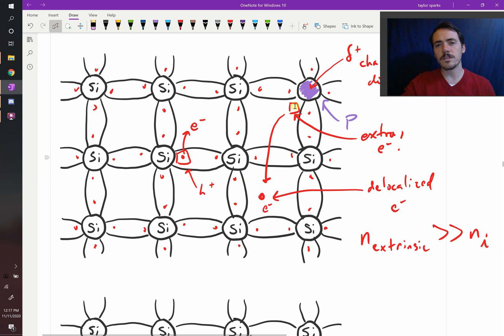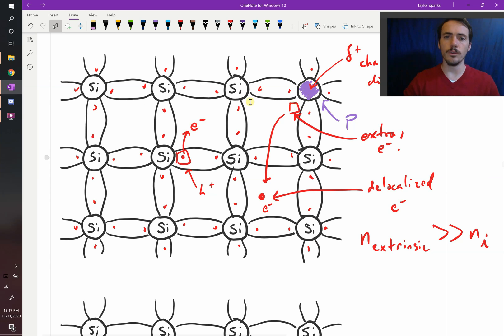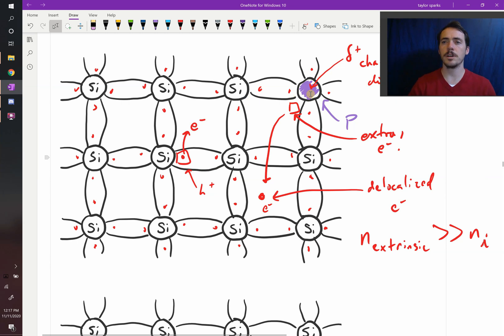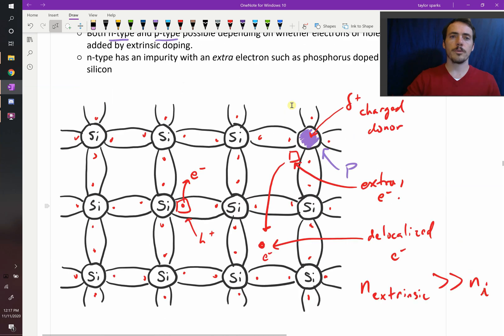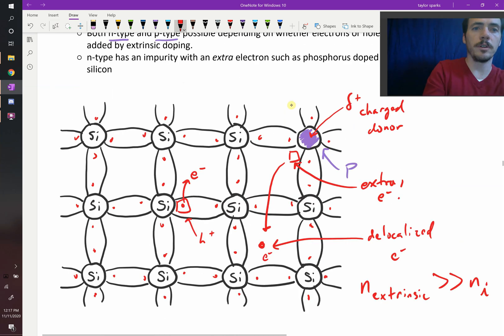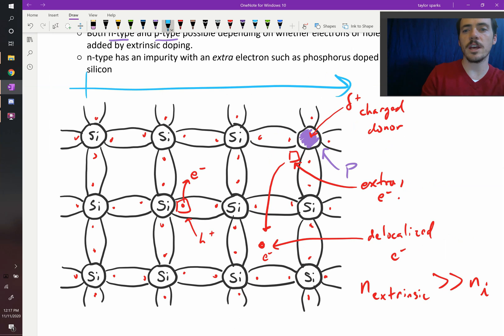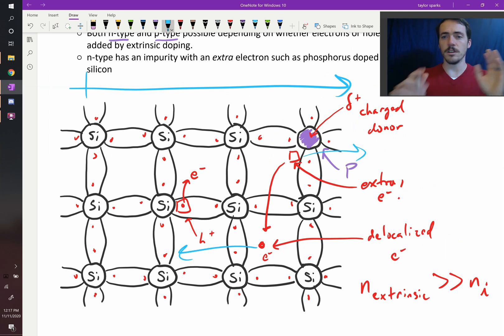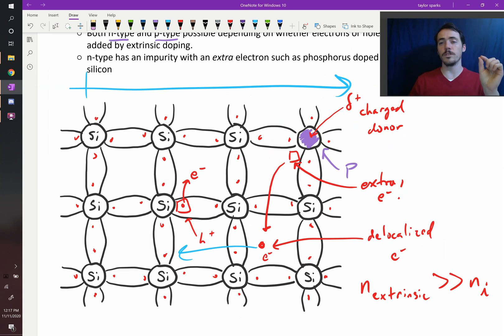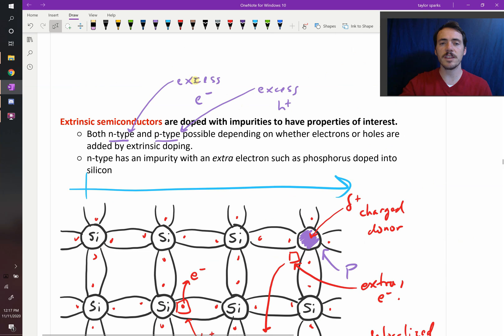Why doesn't the hole move here? Well, this hole is a site tied to the phosphorus atom — it can't move to a silicon because silicon doesn't have that spot. That's tied to this phosphorus atom because it is a group 5 instead of a group 4 atom. Previously, when we had a big electric field applied, the hole would go one way and the electron the other. That is not the case here — only the electron moves. You don't get the hole contribution. Therefore, you've made it excess electrons instead of an equal number of electrons and holes.